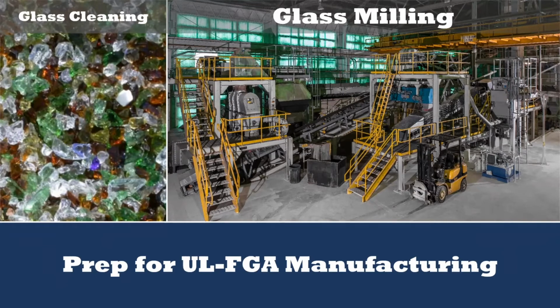And when you mill the mixed color glass cullet, when you take it down to that particle size, the glass can't reflect light in the same way. And so we truly are left with this off-white, creamy colored powder that does look very similar to all-purpose flour. All right, so we do that using a specialty glass mill. You can see the mill set up and part of the classifier here in this photo on the right. It's a pretty efficient mill. And at the end of this process, we're able to store any of the glass powder that we make in silos that are located outside of our building. But everything in terms of the glass processing, so cleaning and milling, is all happening under roof.